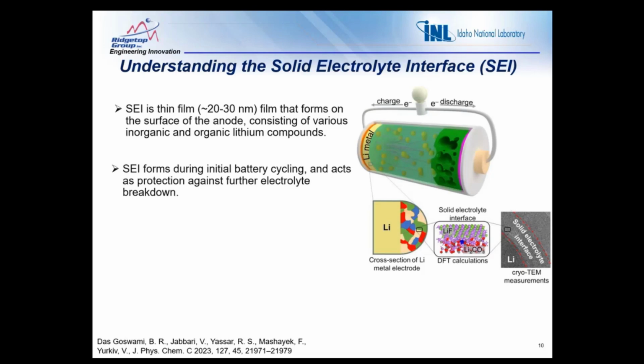While the SEI is beneficial, providing stability and enhancing the battery's lifespan, it also presents a critical challenge. During discharge, the SEI can decompose, releasing a significant amount of heat. This decomposition becomes a key factor in thermal events, particularly under conditions of high stress or failure. In this research, SEI decomposition has been assumed as the primary trigger for exothermic heat release. This heat generation, if unchecked, can escalate into thermal runaway once chain reactions start to occur.